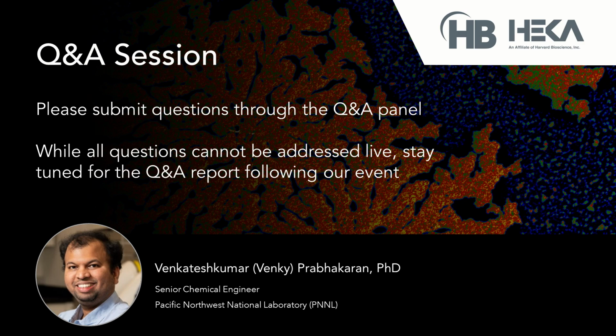And you probably can do the measurement in high vacuum, but not ultra high vacuum. That means if your pressure is above 10^-5 torr, it's fine, I would say.